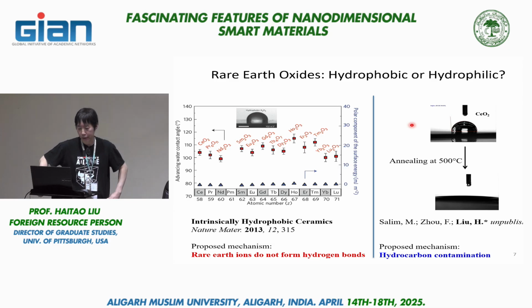This is a paper in 2013 from a group at MIT where they report hydrophobic ceramic material. Now that was a big deal at that time because in a lot of industrial applications, the heat exchanger would prefer a hydrophobic coating. Why is that? Because if you are dealing with condensation of water vapor, you prefer a hydrophobic interface because that creates water droplet condensation. There's a difference between water condensed into droplets versus water vapor condensed into a water film. A hydrophilic surface will produce film-wise condensation, and that apparently reduces heat exchange. So you would rather have droplet condensation so that water can be removed quickly.